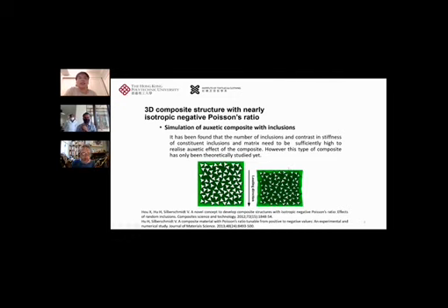Okay. I think there is something quite confusing here in the fact that the effect is a geometric effect and comes from the fact that the white material, be it void or whatever, is a lot more compliant, and therefore it squeezes in a funny shape. In the experiment you have made, in order to get these gaps, you have to enclose them first, obviously. So you have to create these shapes. But the carbon fiber is very, very stiff, and it is kind of preventing the closing of the geometry. So that's why you've got two competing effects here. I'm not sure, but something is a bit weird in the way you are pushing it, I think.